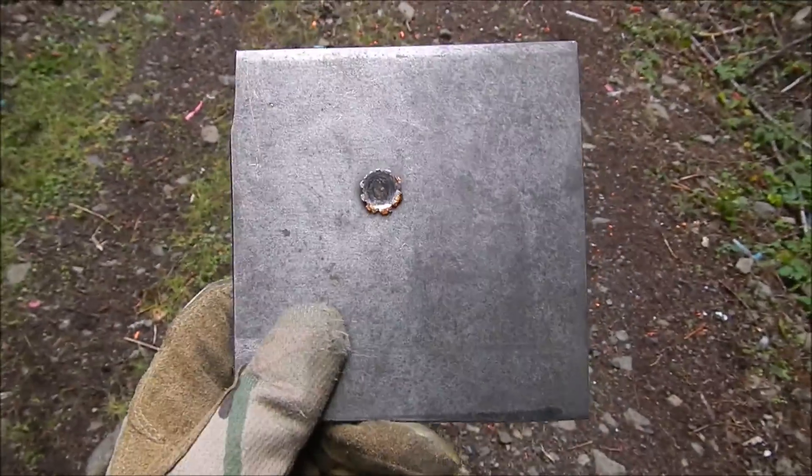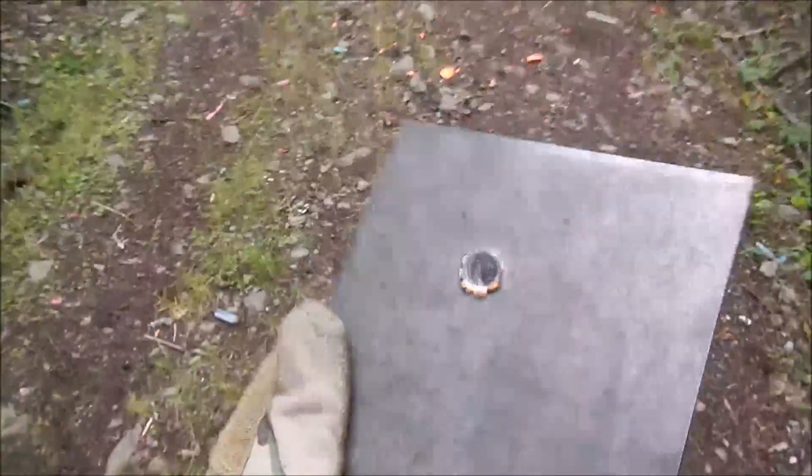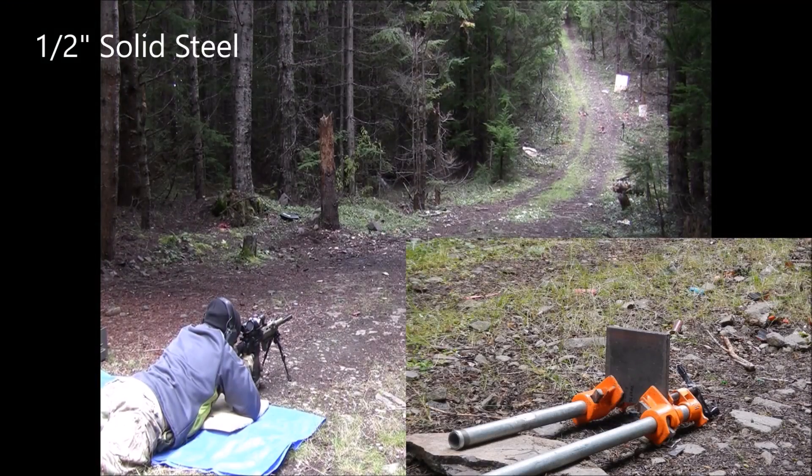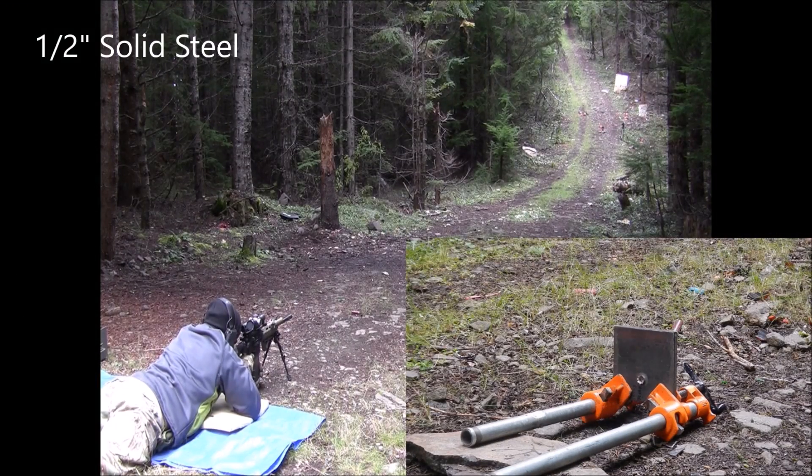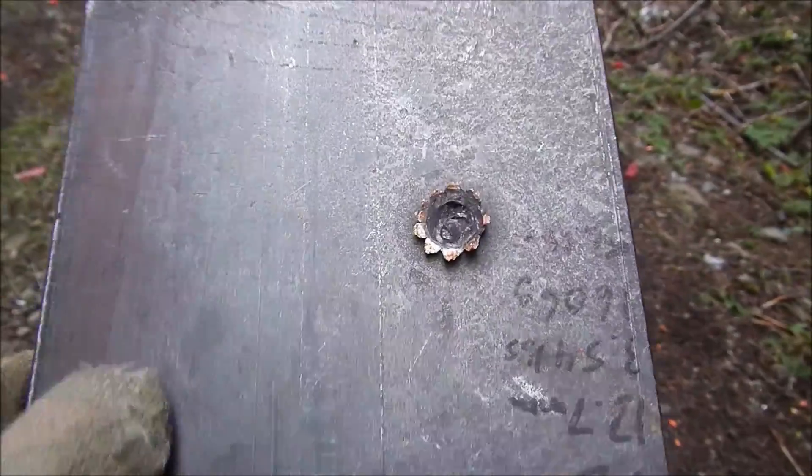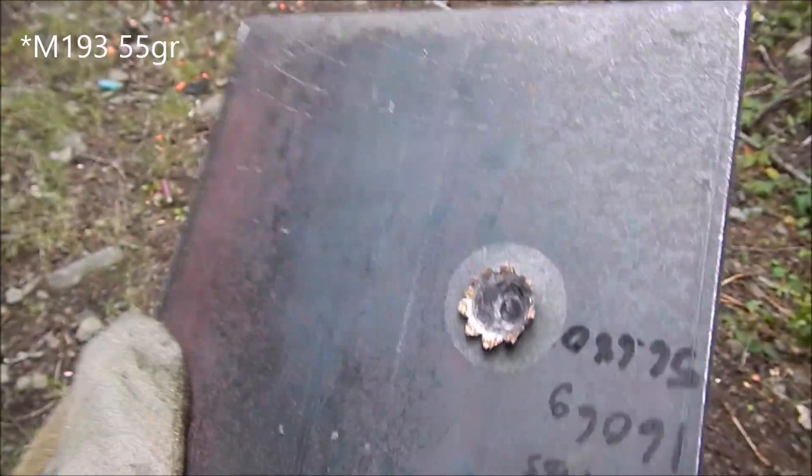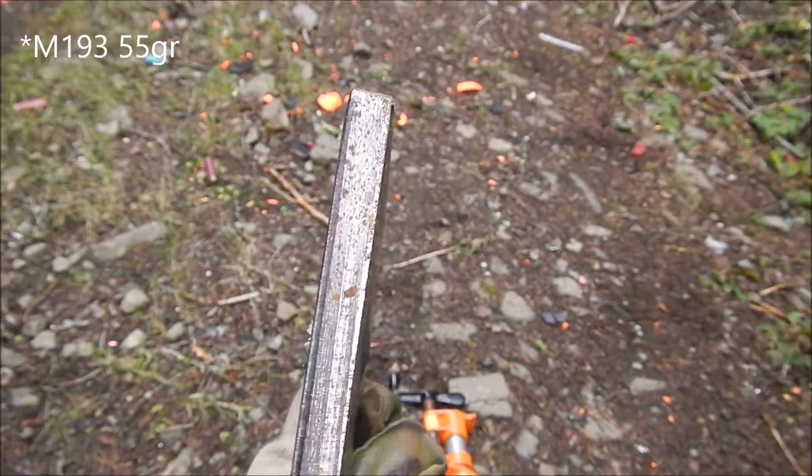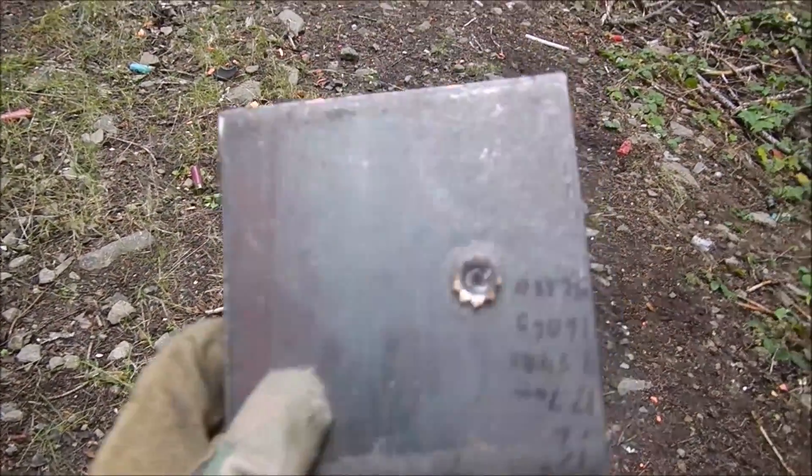Looks like it was not penetrated. It left a big bulge in the back, but that M193 round was not enough to punch through a 1/2 inch of mild steel.